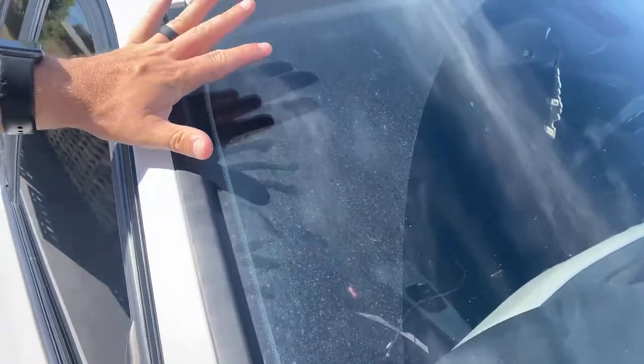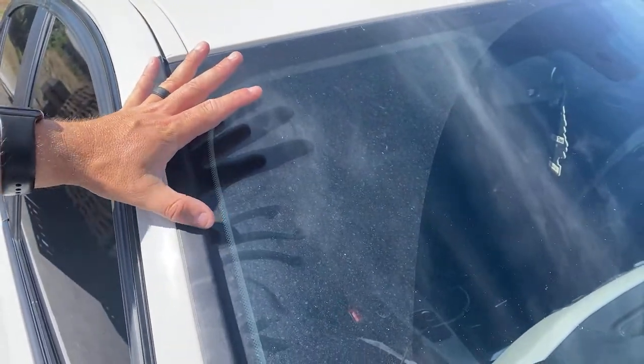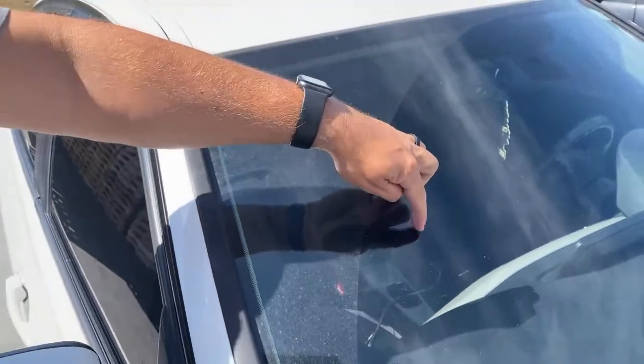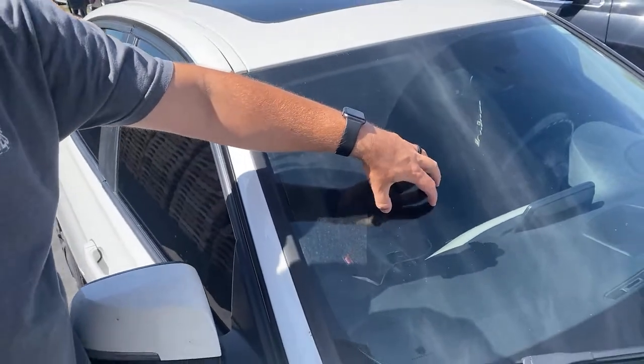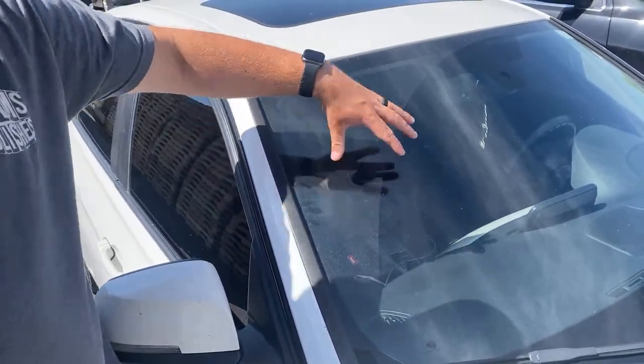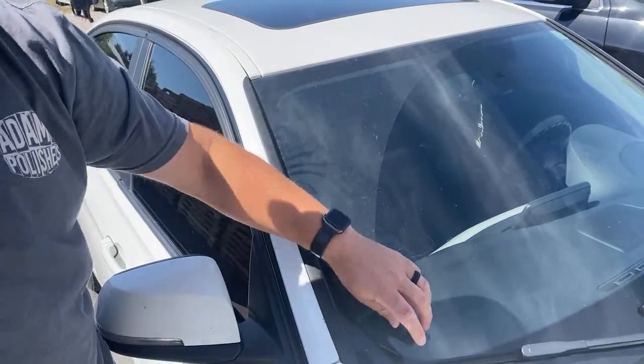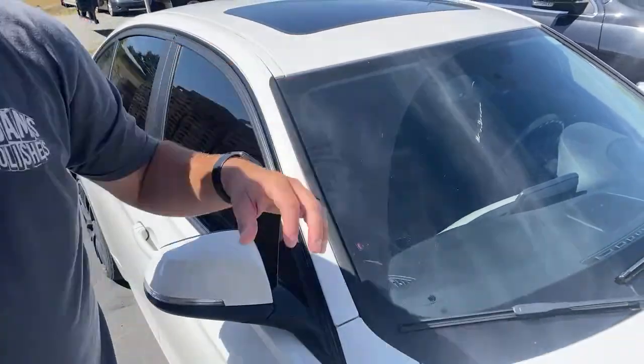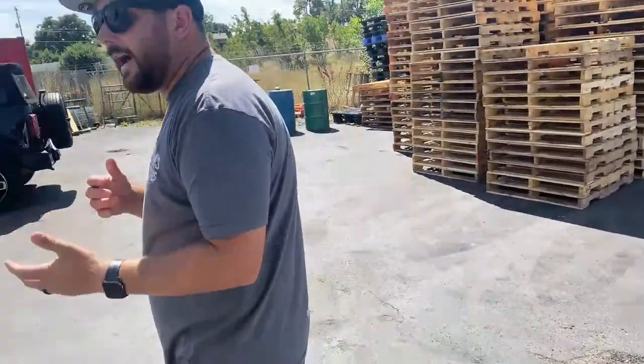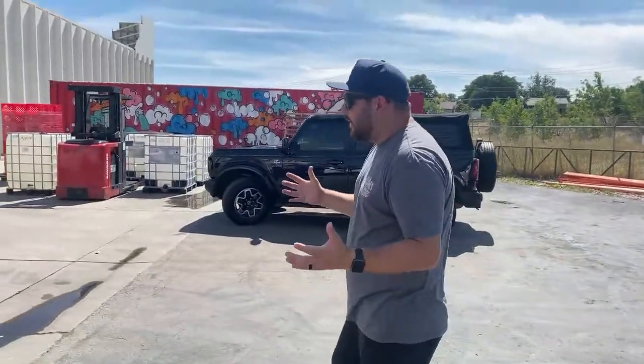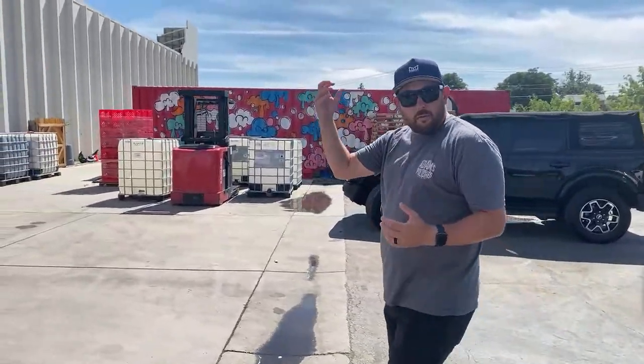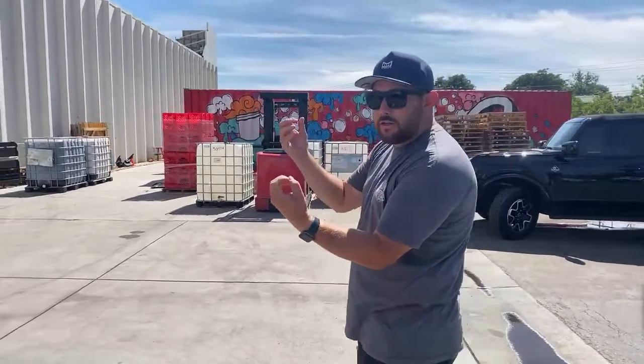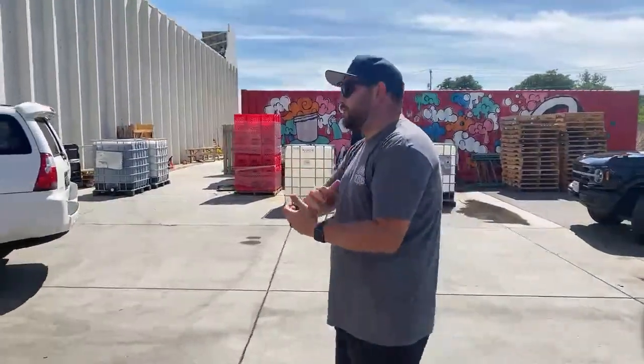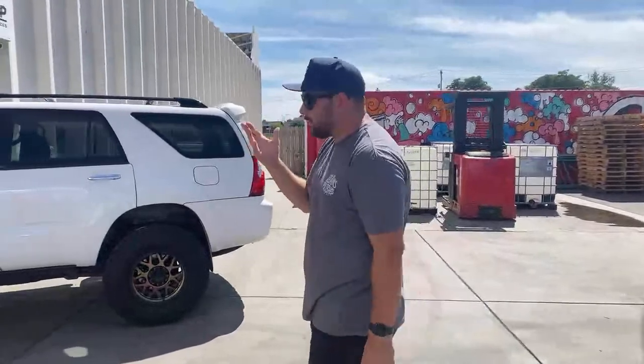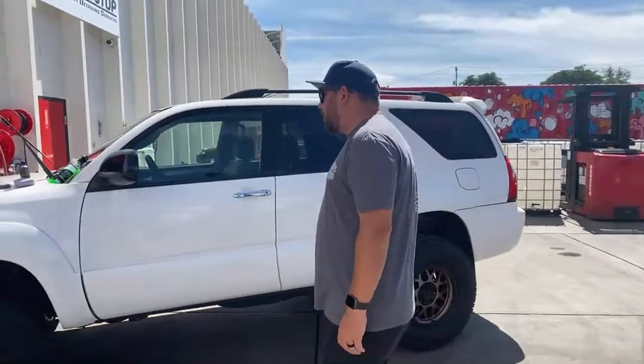So then what we started seeing with the graphene ceramic coating is that the coating was being abraded away on the area that you're trying to look out of, but in the areas untouched by the wiper blades, the coating would still be there. And you could see a very distinct line, even when your car was clean, of an area where the windshield was coated and an area where the windshield was now not coated because it was being abraded away so much from using your windshield wipers.